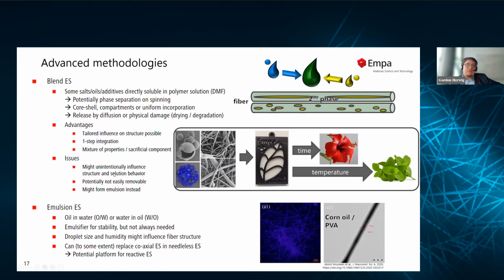Issues, of course, are that you can influence your whole spinning behavior like this, which might go against what you are used to on your machines. It's not necessarily easily removable. Imagine there's a proper blend, then the inner compartments are not actually easily accessible. And as I said, it might actually form an emulsion instead, which complicates the electrospinning, especially on a Nanospider somewhat, but not necessarily if the emulsion is relatively stable.